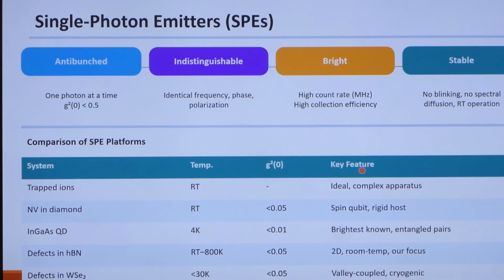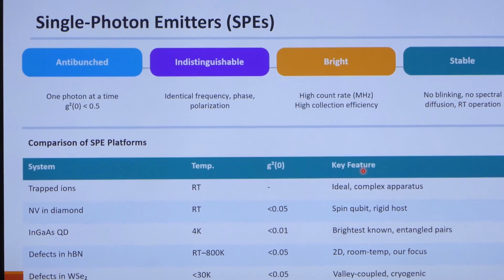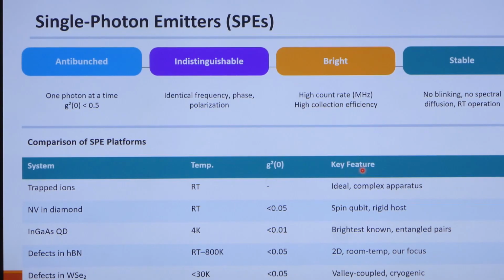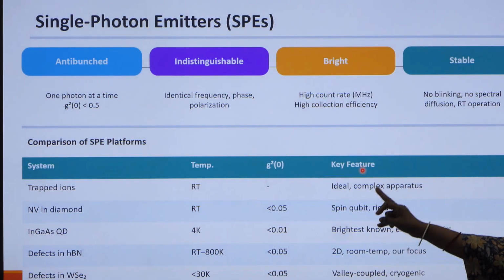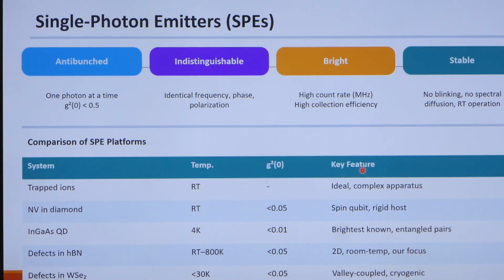Now you have these single photon emitters. There is a parameter, g2, that only the equipment can measure; we cannot measure it by hand. That equipment will say that g2(0) is less than 0.5, meaning a single photon is coming from the excited state when it goes to the down state. If it is more than that, it will say more. And you have values like g2, 0.05, 0.01, 0.05; accordingly you have the key feature.